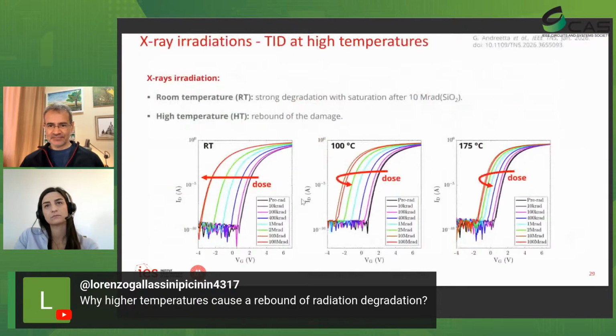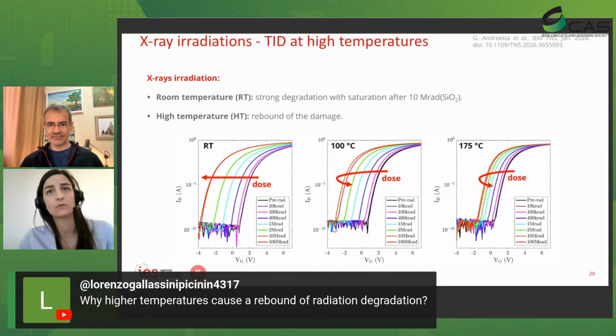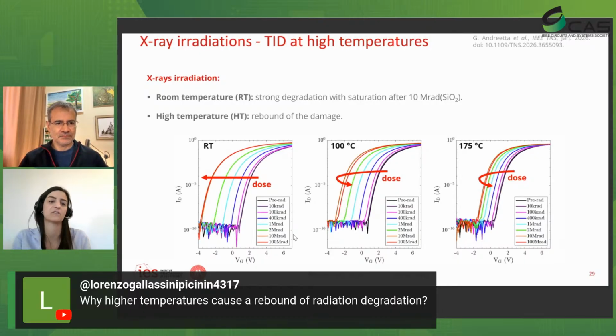Yeah, so of course, the higher temperatures allow some of the damage to anneal. You have to think that the last curves here were performed, for example, one at 10 megarad and the other at 100 megarad. So with respect to the previous points, the device was exposed to radiation for a much longer time. And so my assumption is that we were simply allowing more time for the annealing process to happen. And so that's why we are observing these rebounds.